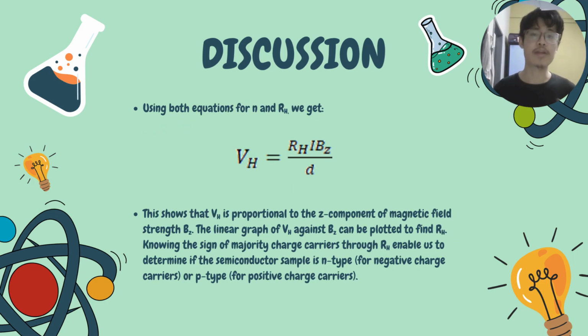Using both equations for carrier concentration n and Hall coefficient RH, we get this equation. This shows that Hall voltage VH is proportional to the z component of magnetic field strength Bz. The linear graph of VH against Bz can be plotted to find RH. Knowing the sign of majority charge carriers through RH enables us to determine if the semiconductor sample is N-type for negative charge carriers or P-type for positive charge carriers.